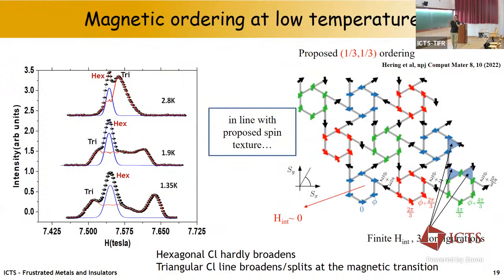So it seems that at this stage we don't need Dzyaloshinskii-Moriya. Now, naively, I don't see why Dzyaloshinskii-Moriya should be very different than in the x equals 0 case, because the bond angles are nearly the same. The chemistry is very similar. Yeah, exactly. But I can tell you that the NMR, for instance, gives you really basically the same lines, the same width. So it should be of similar order as there. And then I wonder how important it would be here, because there it was shown to be really large. So this is clearly something that has to be investigated.